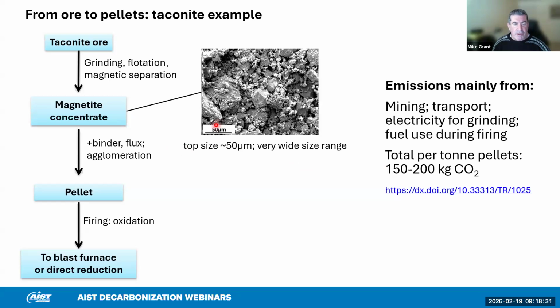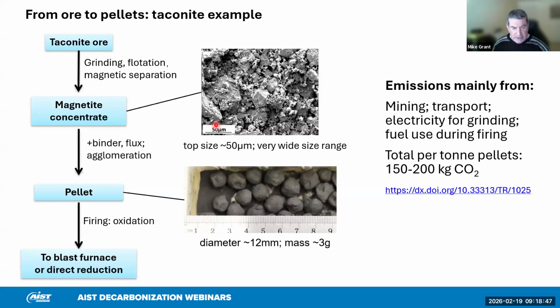And this, of course, is not suitable for the process. So we have to then agglomerate it again. So we add a binder, that's typically a type of clay. We pack it together in little balls, and these become sinter or pellets, as you can see pellets in the photograph here. And we need to do this because we need to be able to pass a lot of reducing gas through the blast furnace or the DRI reactor in order to make the process function.